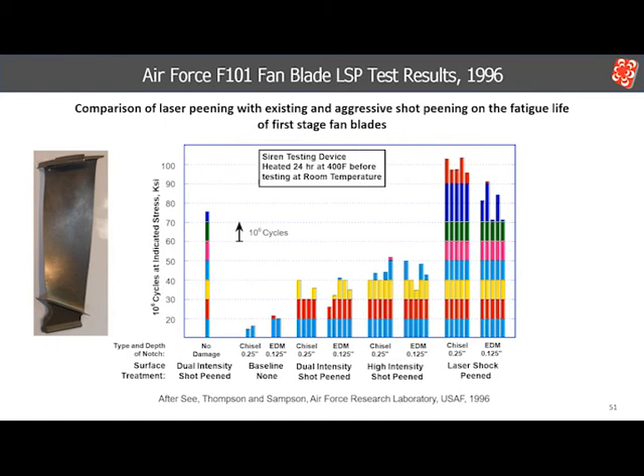The blades were tested on a siren testing device at a very high frequency after being held 24 hours at 400 degrees Fahrenheit. The testing began at a stress amplitude of 20 ksi, then stepping up the stress by 10 ksi increments at 1 million cycle intervals until failure. The new blade test is on the far left. The baseline damage test had a very low life. The high-intensity shot peening showed a slight improvement over the dual peen condition, but still had much reduced fatigue strength after being damaged. By contrast, the damaged laser peen blades had a fatigue strength higher than the undamaged blades with the chisel notch and about the same as the undamaged blades for the EDM notch. This result was due to compressive stresses being high enough through the thickness of the blade for some distance from the leading edge. The compensating tensile stress was at the rear of the laser peen patch, well away from the leading edge. Therefore, any incipient crack in the leading edge was clamped closed and unable to grow.